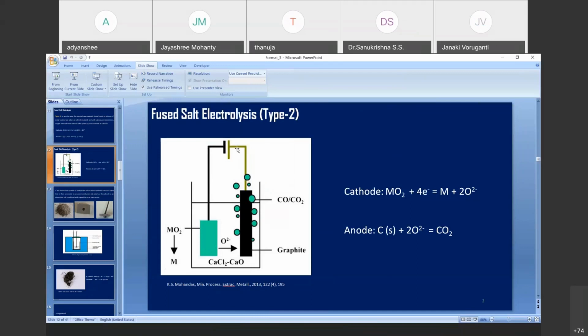And this one is the carbon anode. It is also connected to a current collector, and this is the molten electrolyte. The molten electrolyte consists of calcium chloride. You can see here, in the Hall-Héroult process, the electrolyte is cryolite, if you remember, and here the electrolyte is calcium chloride. So calcium chloride and CaO.